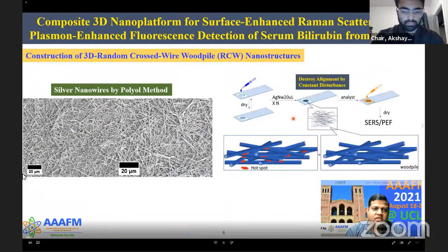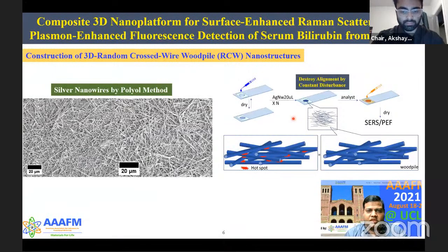So to construct the 3D random crossed-wire woodpile nanostructures from silver nanowires, we synthesized silver nanowires by the well-known polyol method. And to construct the 3D nano platform, we first sprinkled a certain amount of silver nanowires onto a glass platform and subjected it to vacuum drying. And we repeated this procedure subsequently so that any sort of alignment would be destroyed, so as to create a wood pile structured silver nanowire. So this represents the structural disarrangement of silver nanowires.